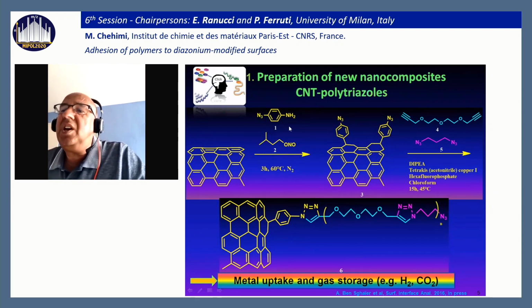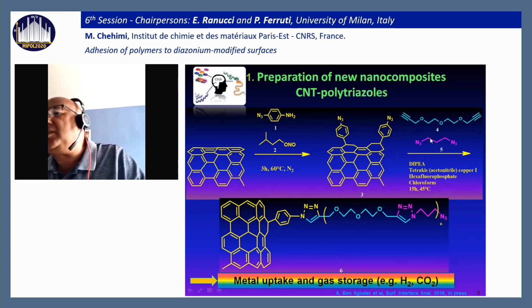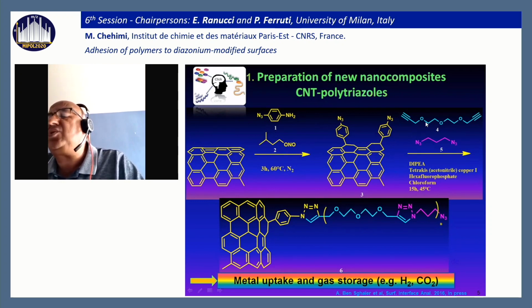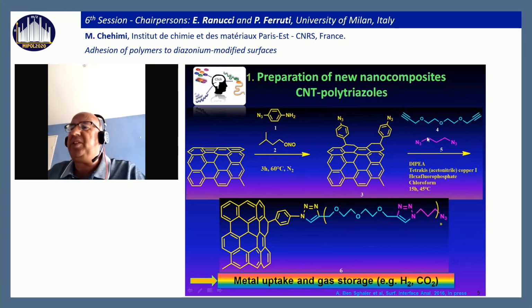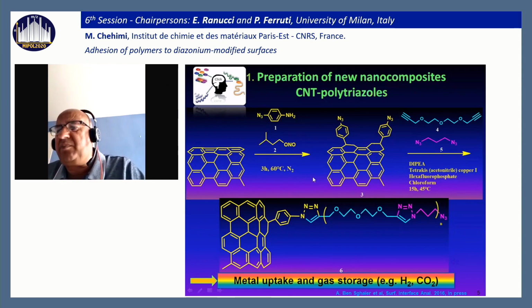We fabricated the diazonium salts of this aromatic amine, so we can easily modify the carbon nanotube with these diazonium salts in isoamyl nitrite. So we diazotize in situ in the presence of the carbon nanotube. We have these nanohybrids, clickable nanohybrids, and we have made the polytriazole using these two monomers, which were prepared in the laboratory. So we ended up with in situ generated polytriazole on carbon nanotubes.